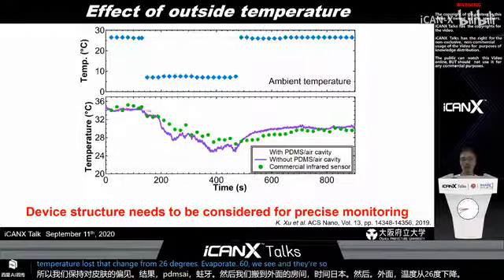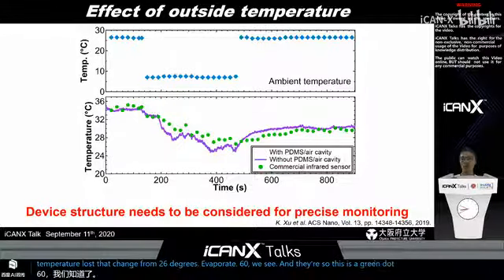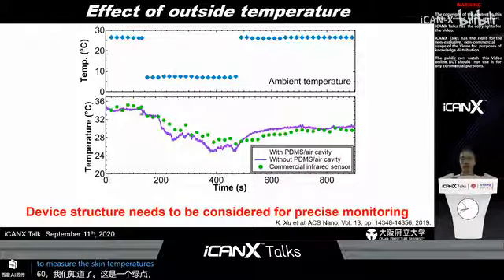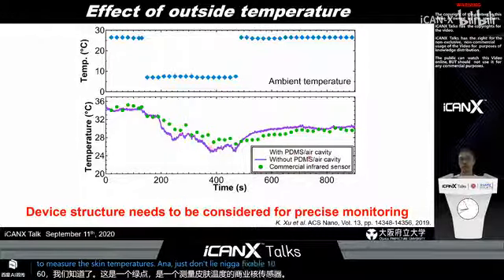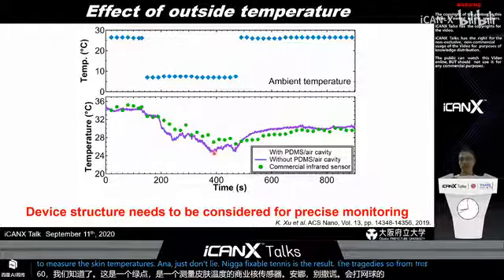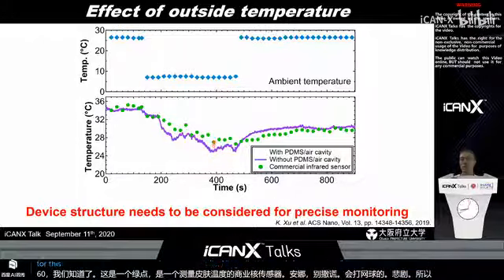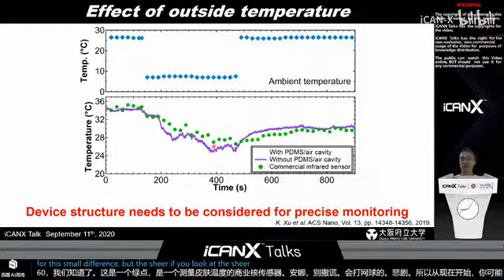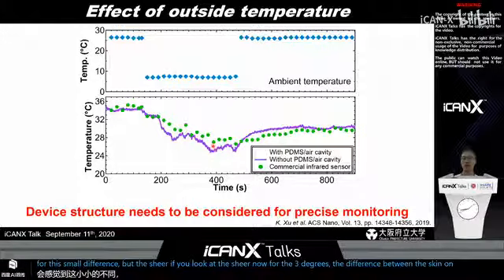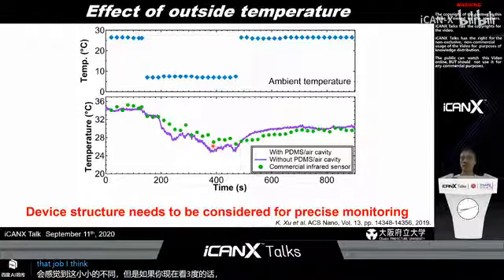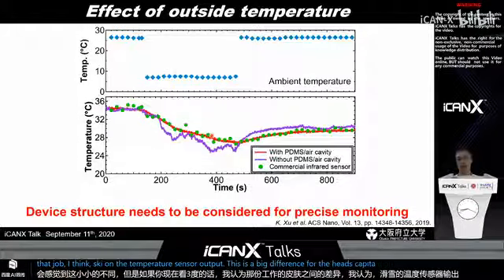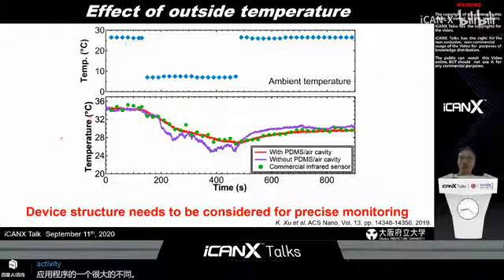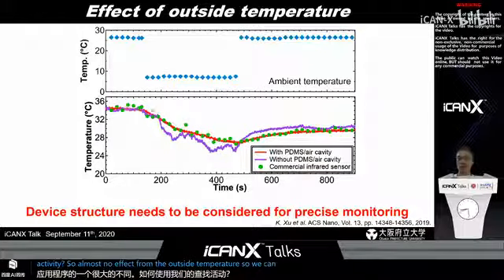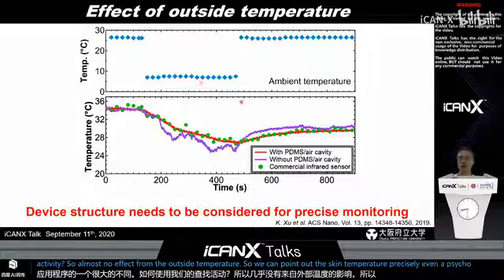And then, this green dot is a commercial infrared sensor to measure the skin temperatures. And then the purple line is the flexible sensor without air cavities. From this result, you may feel, oh, this is a very small difference. But if you look here, actually, roughly 3 degrees C difference between the skin and the temperature sensor output. This is a big difference for the healthcare application. However, by applying the air cavity, there is almost no effect from the outside temperature. So we can monitor the skin temperature precisely, even when the outside conditions change like this.